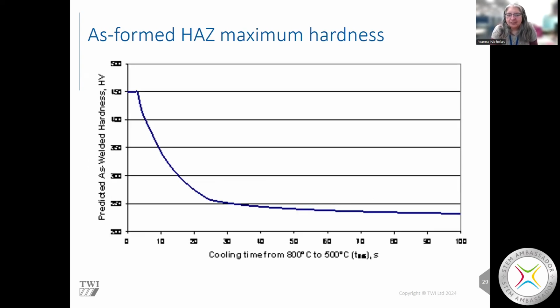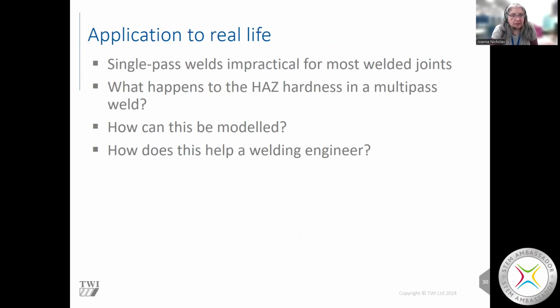Both the models result in this sort of approach, whereby we've got this high hardness, low cooling time model, which then transitions not as a straight line as the concept, but in a sort of curve. And then we actually don't end up with it. We end up with some kind of continual softening with very large cooling times, which is more accurate to what happens in real life. So for applications to real life, works beautifully for a single pass weld, but that's not very practical for most welded joints.